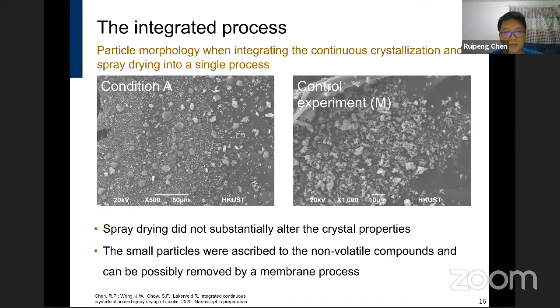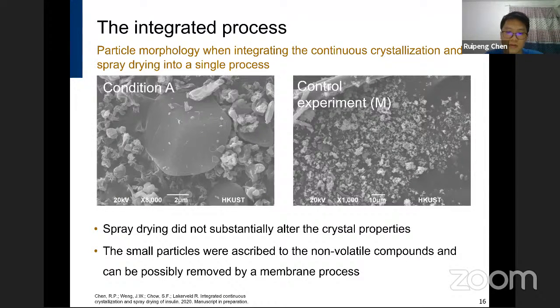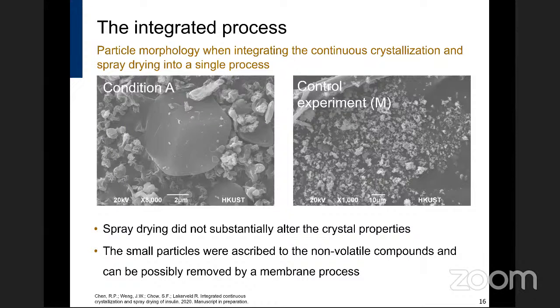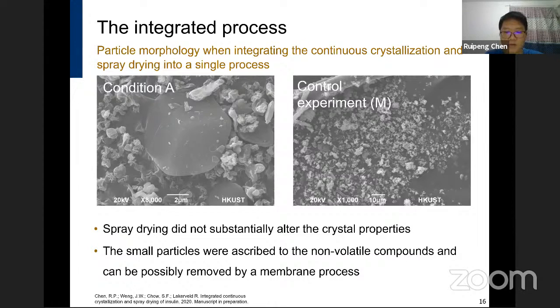So for the larger particles obtained under condition A, the size and morphology were consistent with the crystals that we obtained from the standalone crystallization. Therefore, this suggests the spray dryer did not substantially alter the crystal properties, as expected. And the small particles that were obtained from both condition A and M have a size of around 1 micrometer and appear amorphous. These are all characteristics of spray drying from a solution. Therefore, these particles were ascribed to the non-volatile compounds, and this can possibly be removed by a membrane process in future work.